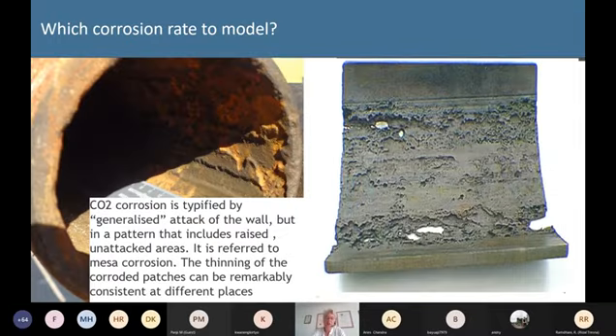With CO2 corrosion modelling, CO2 corrosion has a very particular appearance. You get used to looking at it, and you understand that it's different from, say, oxygen corrosion or acid corrosion, because you have areas which appear to be unattacked. You've got flattened areas, which you can see on the left sample here, and then you've got deeper areas which are all remarkably uniform in depth. They all corrode down to around the same depth. This is what we call mesa corrosion. It's a term that got established for this type of corrosion, and I call it generalized attack.